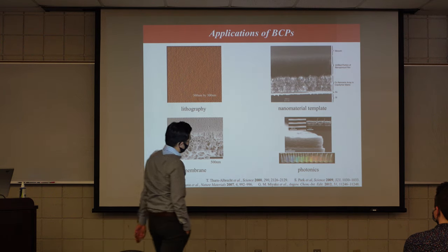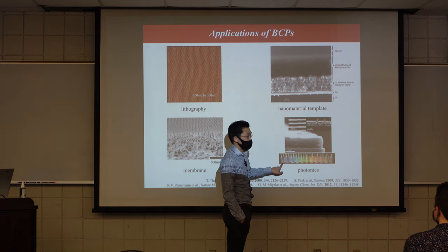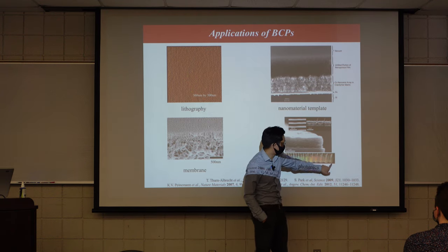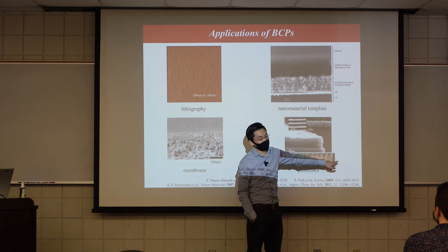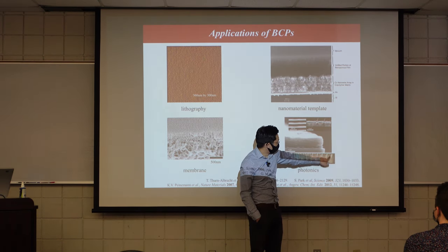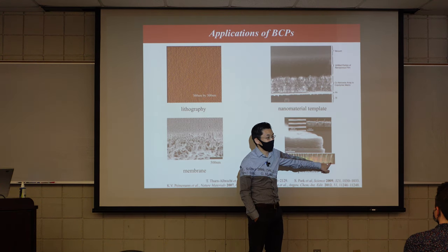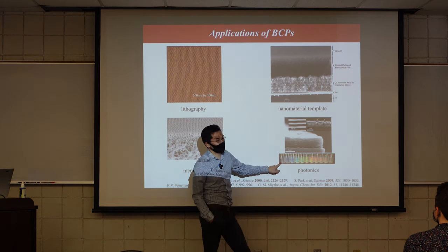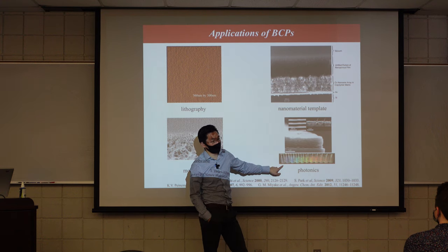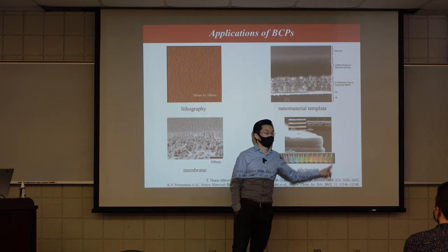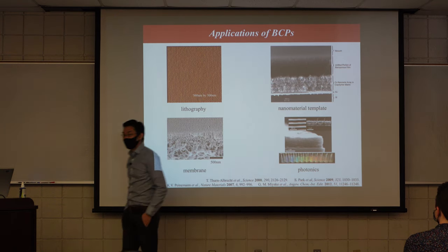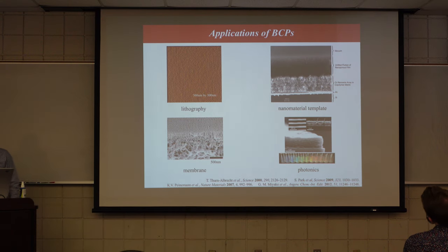They actually show that high molecular weight bottle brush will self-assemble. Here is high molecular weight. It will self-assemble into domains up to 200 or 300-ish, and it will interfere with red light. You could also self-assemble into low periodicity. It will interact with low wavelengths, which is in the blue light region. Now you can blend those two to create a rainbow-like color because they can co-assemble into different domain sizes.